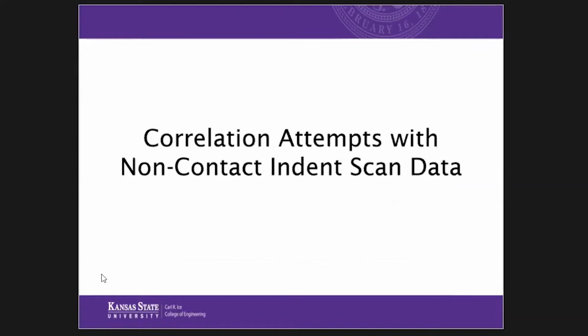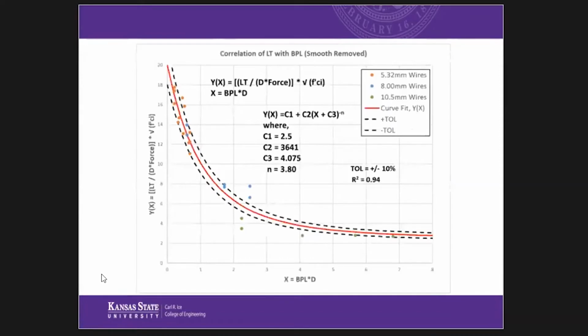How about the non-contact indent scan value? We do something similar. On the left axis, we have the transfer length divided by, this could be pi d or diameter, it's basically linear with diameter, times the force, divided by the diameter times force times square root f'c. And on the x-axis, we just have bite per length times diameter. And R squared is very good, 0.94. You see some of these points are lying a little bit out, and these are the 10.5 mm wires and the 8 mm wires. And some of that is due to, I think, just the lubricants that are there.